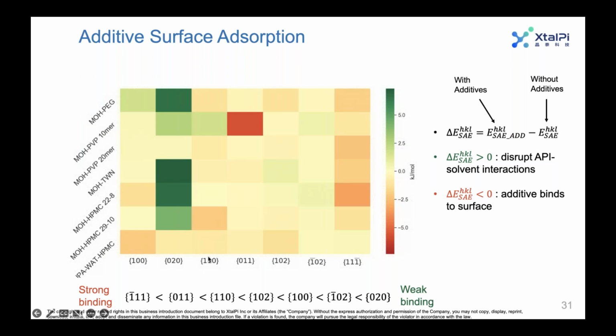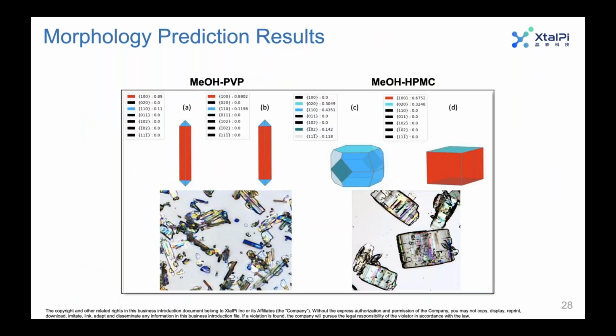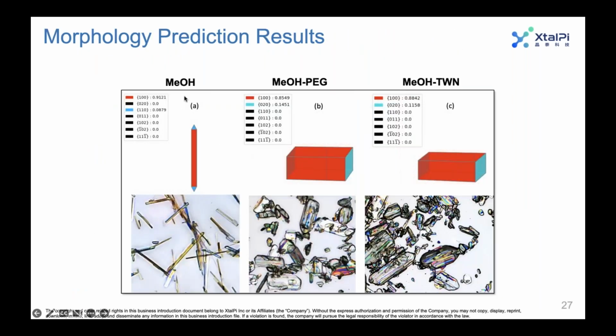And we saw something interesting here. So if I go back to the first example I gave of MEOH, remember that we have this 110 face, and that disappears once we add the polymer. So what we realized is that changing the growth rate slightly has a profound effect on certain faces. So for example, when you add the polymer, you essentially turn off the 110 face. So you have a real face that you're turning off. So now that's a virtual face, or what we would call a real to virtual transition.